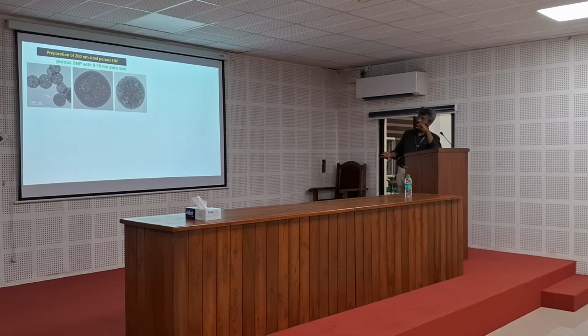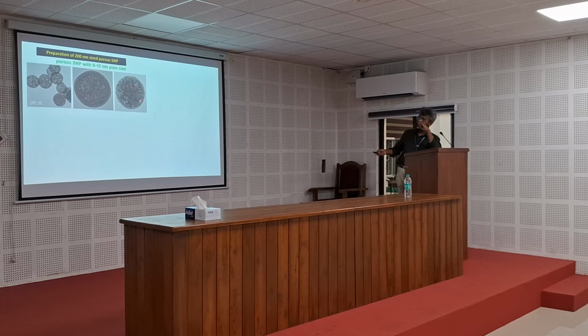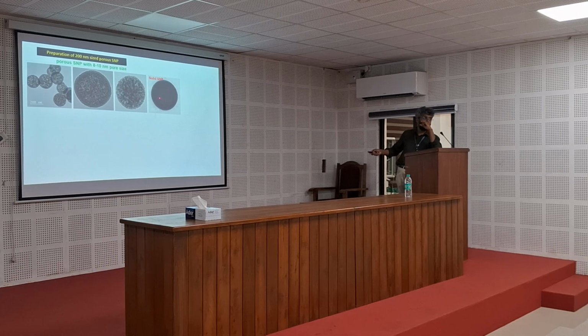Finally we optimized and came up with a successful, our planned nanomaterial. This is high porosity, approximately 10 nanometer in pore size. You can see these small white things inside. These are nothing but pores. And this is highly biodegradable also. So this is a comparison image. The earlier data I showed was with the solid nanoparticle. Now you see this image, the contrast. This is a highly porous material and this is highly biodegradable. This one is not biodegradable.